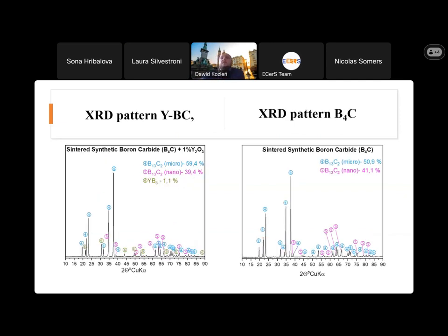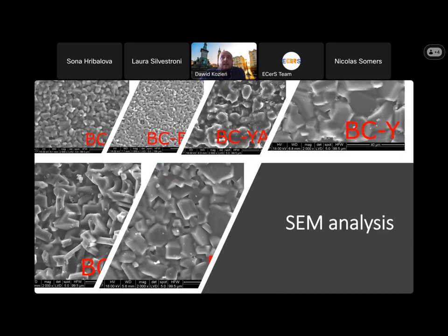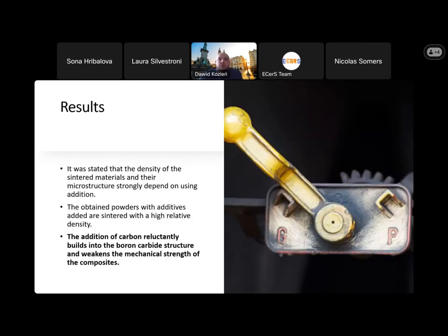The same problem with the YAG, of course, and we obtained some results, and we can say the same in this image: the microstructure of sintered bodies strongly depends on the chemical and phase composition of the powders. Sintering was very problematic, maybe not as good as we assumed, but still we have some results to think about what we want to do next.